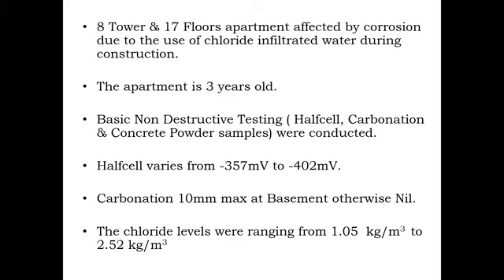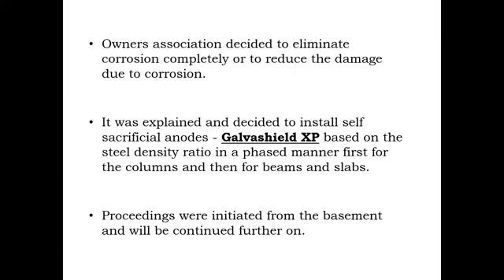But the chloride content, if you look at it, is 1.05 kg to 2.52 kg. In this sort of situation, while making the concrete itself, the water had a lot of chloride. So the whole core concrete has chloride content, where you will not be able to remove the chloride contaminated concrete and go with a new one. So the best thing is to go only with a sacrificial anode system.